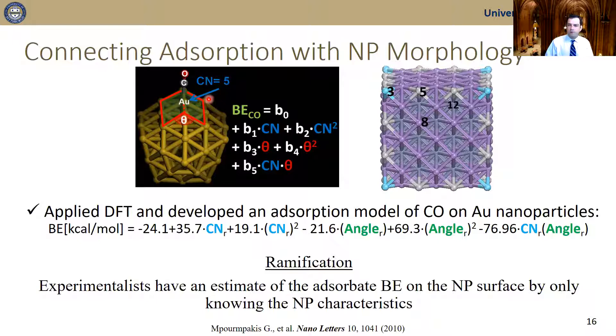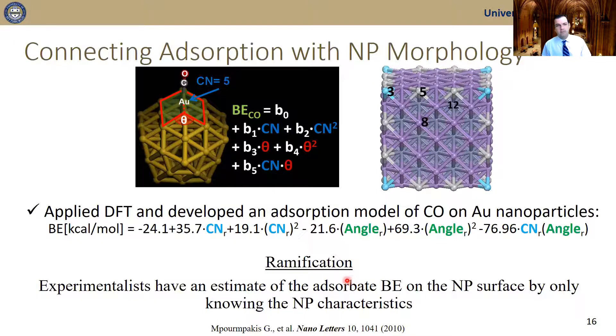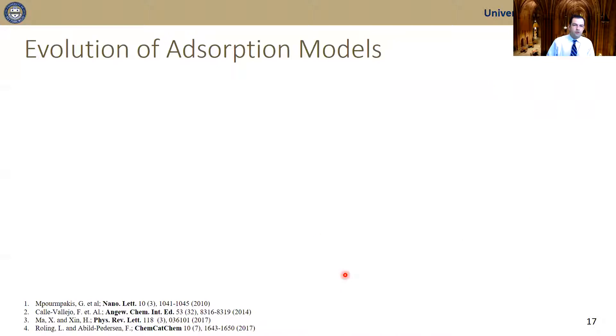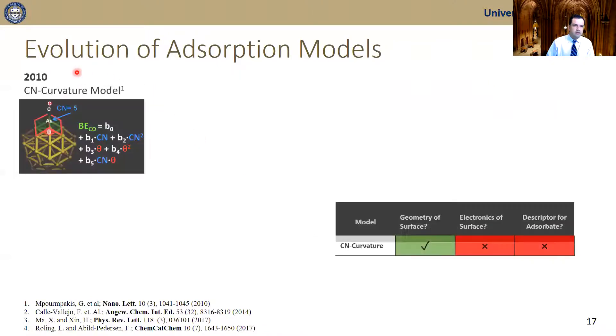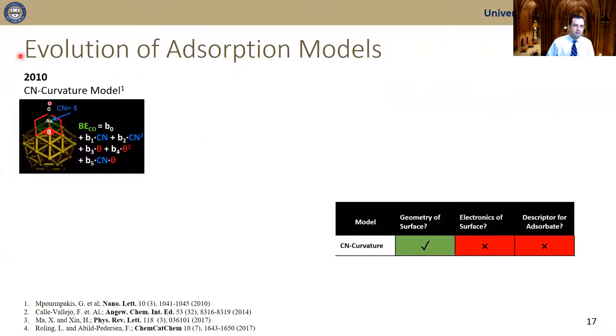What is the importance of this model? Experimentalists can now estimate the adsorbate binding energy on the nanoparticle surface by just knowing the nanoparticle characteristics, which can come from spectroscopic studies. Our model was developed back in 2010 and takes into consideration structural characteristics of your catalyst.